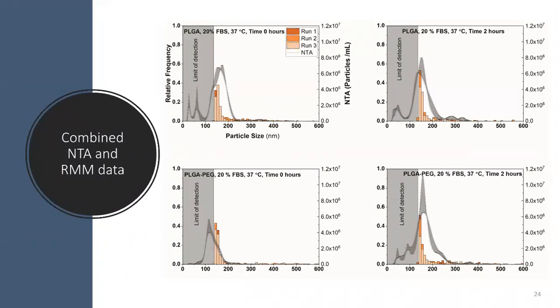If we then look at the shape of the data that we get from NTA and that from resonant mass, we can see that the shapes map each other fairly well. And that strong agreement is quite a good thing to see between these two techniques because they operate in two different ways. So nanoparticle tracking analysis is an optical technique, whilst resonant mass is not.